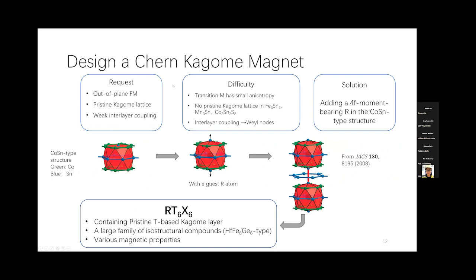So based on those theoretical models, how can we design a Chern kagome magnet? Basically, we need out-of-plane ferromagnetism. We need a pristine kagome lattice. We also need a weak interlayer coupling. But the difficulty for the transition metal-based kagome lattice is that usually the transition metal has a small magnetic anisotropy, and there's no pristine kagome lattice in other kagome magnets. And also the interlayer coupling is really strong. So that makes the sample become a Weyl semimetal.